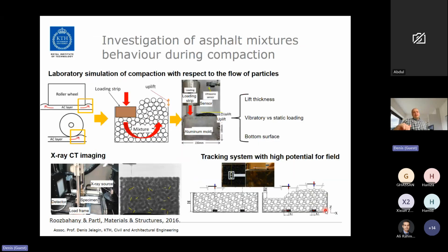So here we have first example, and that's from a PhD project at KTH, which finished roughly 5 years ago, where a new test method to study flow of asphalt mixtures during compaction has been proposed. And the idea there was to remedy shortcoming of not having test method which deals with mixture compaction in kind of semi-confined situation. Everything we have in the lab so far confines mixture completely. Think about gyratory compaction, where one has a top plate which covers specimen 100%.